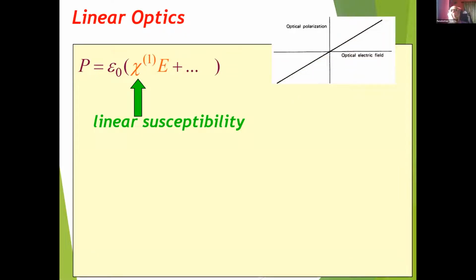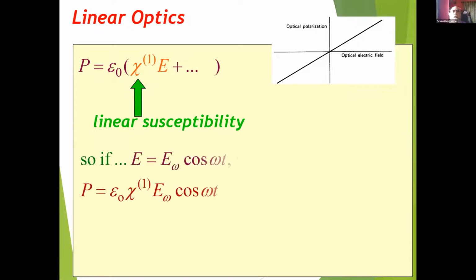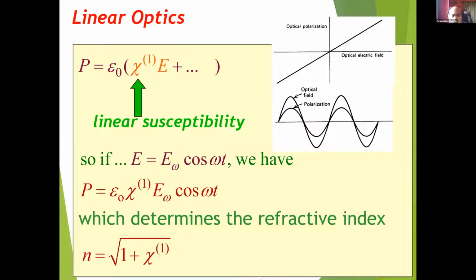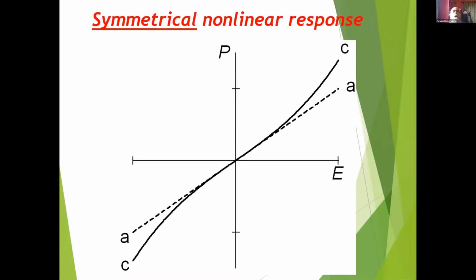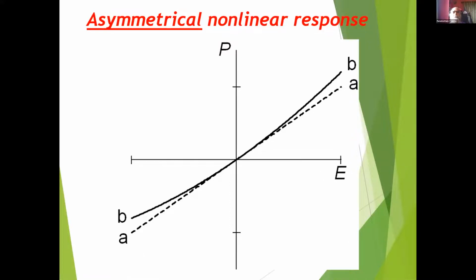Therefore, if you make a plot of the polarization as a function of the optical electric field, it is just a linear function. And of course, we can get the refractive index, which basically comes from the equation, square root of 1 plus chi1. Now, for the symmetric structure, the polarization as a function of E is a straight line, but for the nonlinear effect, it could also be symmetric. You see curve c is for the nonlinear one.